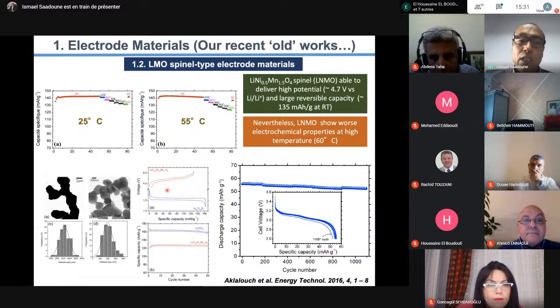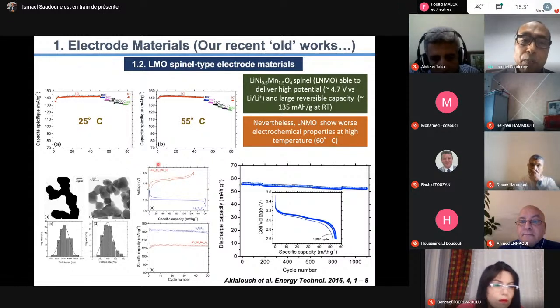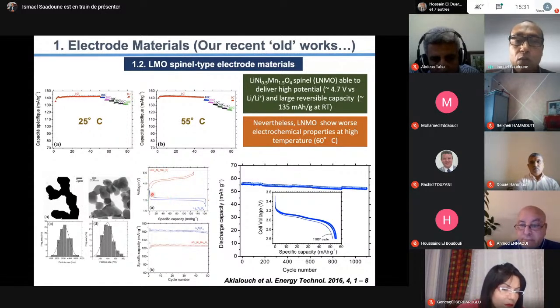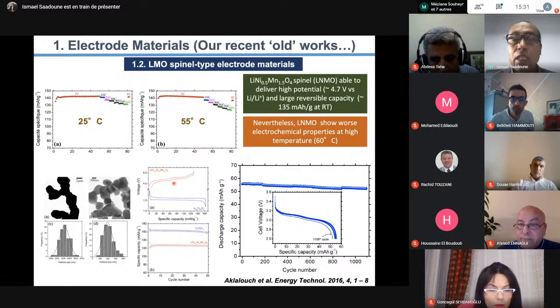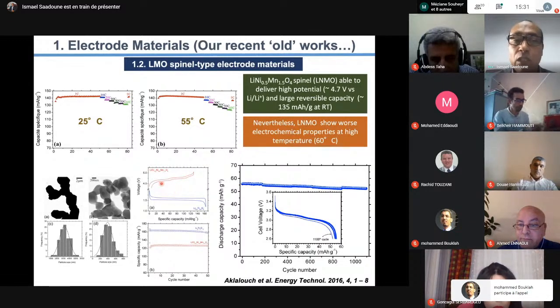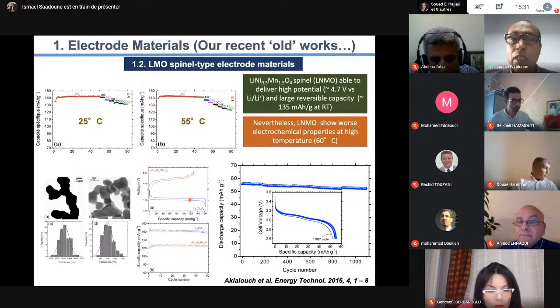What we do here is build the half cell - remember, half cell with our spinel and lithium. You see we have voltage around 5 volts, and we use an anode material called LTO, with flat voltage at 1.5 volts. The next step is to build the full cell, using this one as cathode and this one as anode. The problem is how to optimize the capacity, how to optimize the weight on the anode and cathode sides.